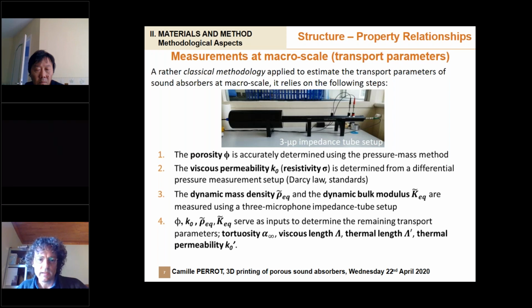What I can mention here is that the more macroscopic parameters you get from direct measurements, the better it is. And you should try to avoid, if you can, inverse methods based on minimization of the cost function. It's not always possible, and you can also get some flags in order to avoid some errors.